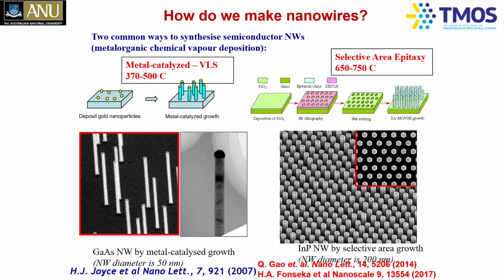During her PhD, she demonstrated atomically perfect gallium arsenide nanowires by developing a technique called the two-temperature growth process. Initially, Hannah started the nucleation process at a high temperature, then reduced the growth to a lower temperature that avoids this tapering of the nanowires. And also, surprisingly, we found that there are twin-free, defect-free nanowires as well. That has been a major problem when making these nanowires, the shape of the nanowires being very tapered. Otherwise, twin defects have been leading to a lot of problems in terms of the performance of these nanowires. And Hannah's work, during her PhD, has solved that particular problem.